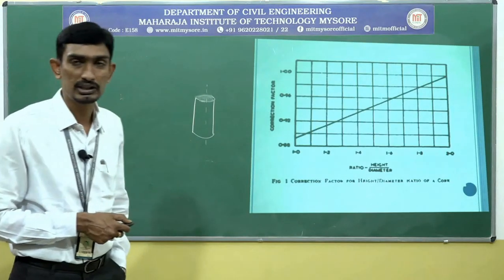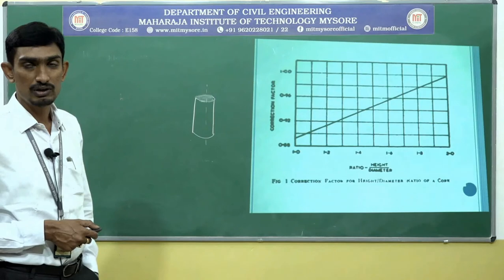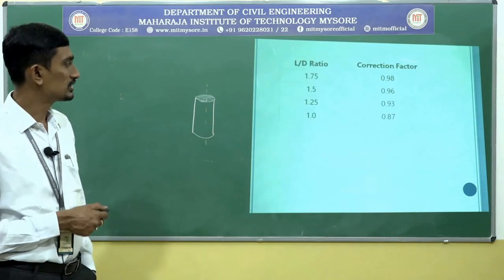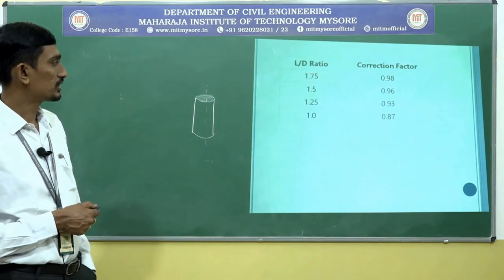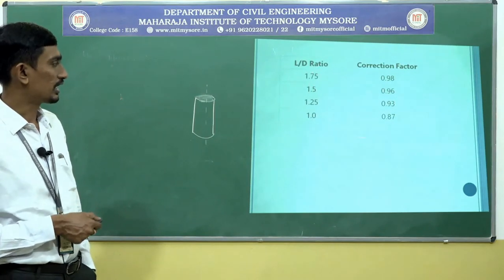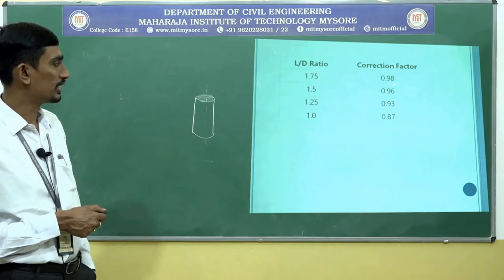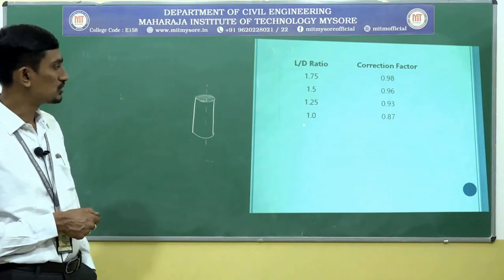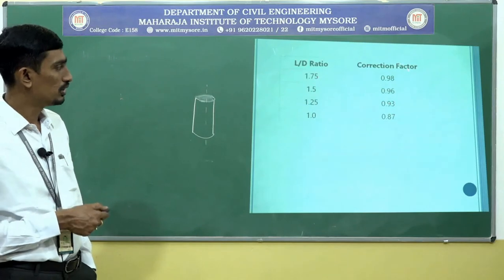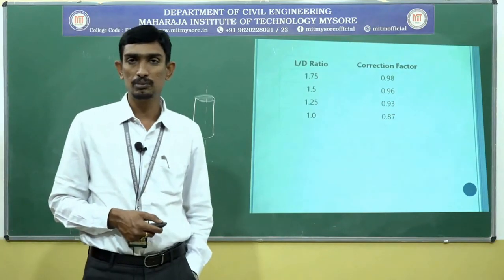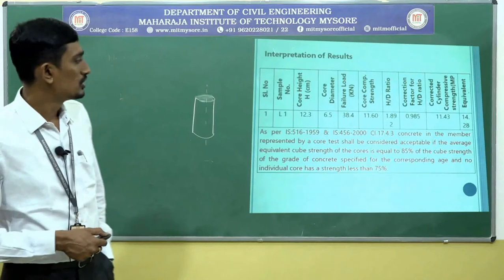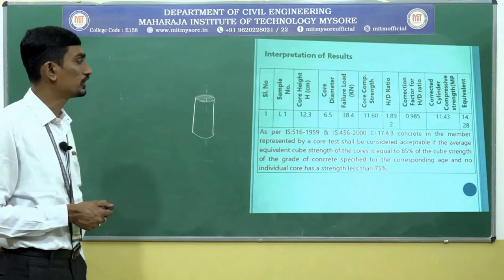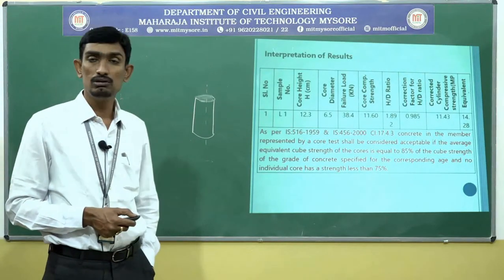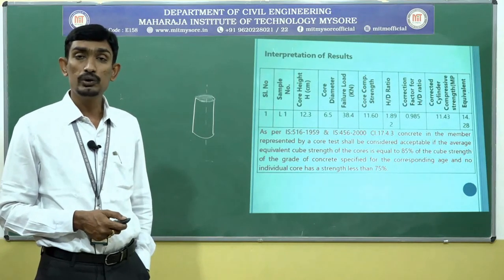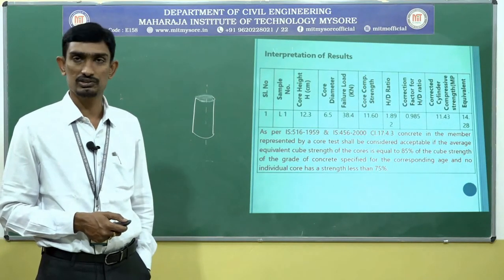This graph is provided in the relevant part of the IS 516 code. And this is the table. Based upon the L by D ratio, this is the correction factor. If it is 1.75, 0.98; if it is 1.5, 0.96; if it is 1.25, 0.93; if it is 1.0, 0.87. Like that you need to apply the correction factors. This is a small table showcased for you in order to teach you how to interpret the results after performing the test.